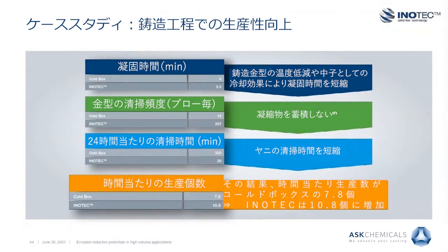Besides the ecological benefit of reducing emissions in the casting process with INOTEC, an increase in productivity is apparent as well. The lack of condensate buildup in the permanent die mold for INOTEC-based casting processes enables lower die mold temperatures, thus faster solidification results in addition to a higher permanent die mold availability because of savings in maintenance and cleaning. These effects overall contribute to a productivity increase of roughly 30% in the casting process at the die itself.